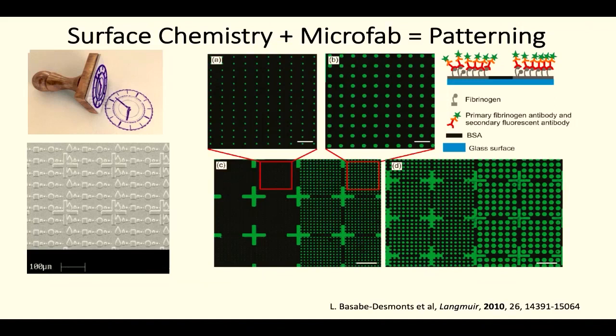What you are seeing in the pictures is a glass slide functionalized with a pattern of fibrinogen, and the fibrinogen molecules have been stained with an antibody, immunostained. So that's why you see the green. Where you see green, that is fibrinogen. In order to make this surface functional, we have to block the part that is black in the image. It is blocked with, for example, BSA protein, just to avoid interaction in those areas.